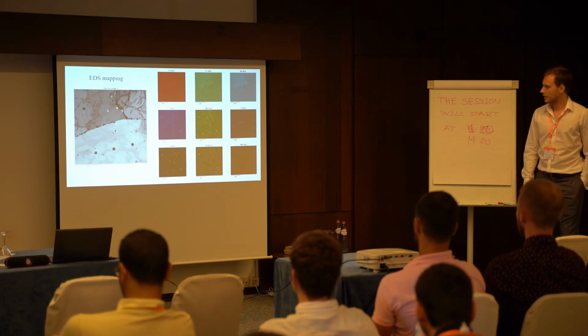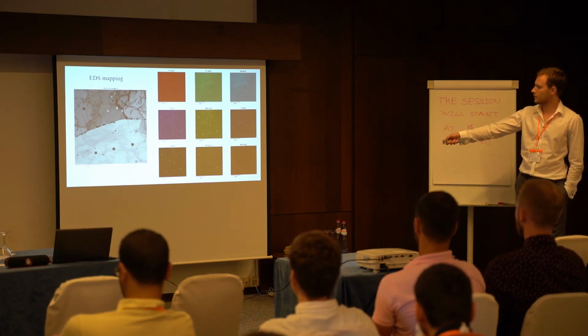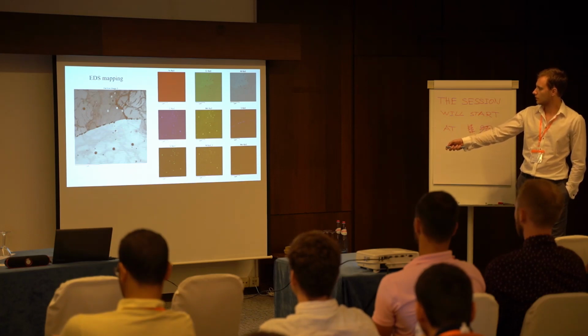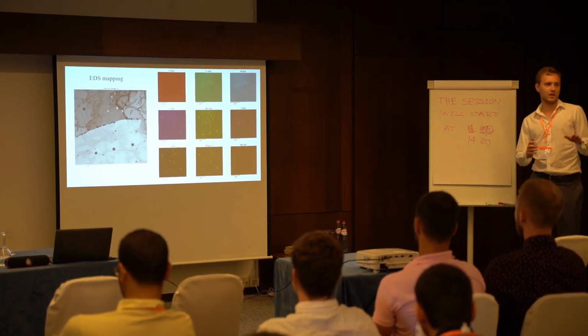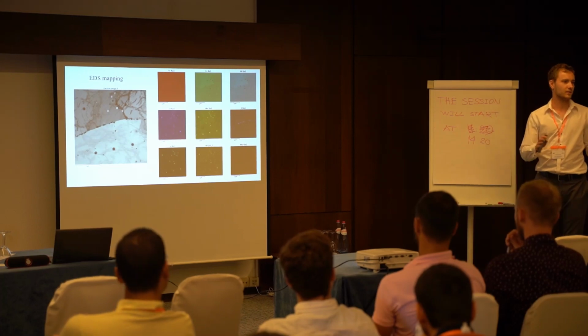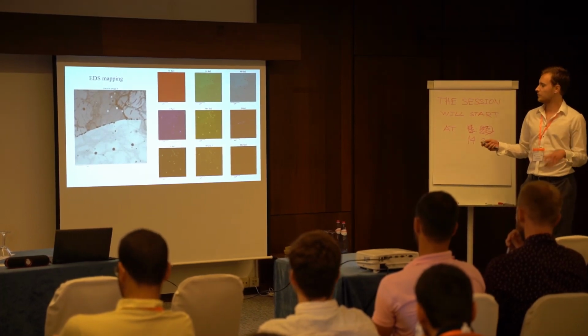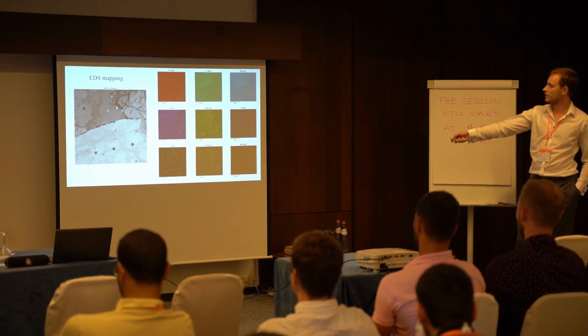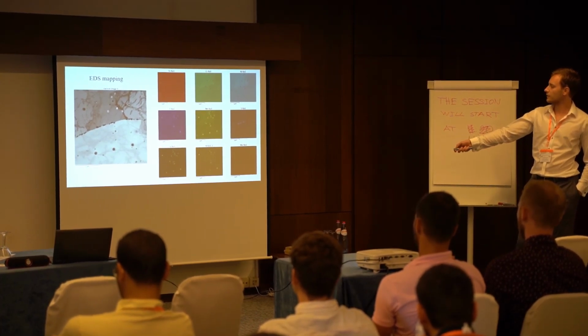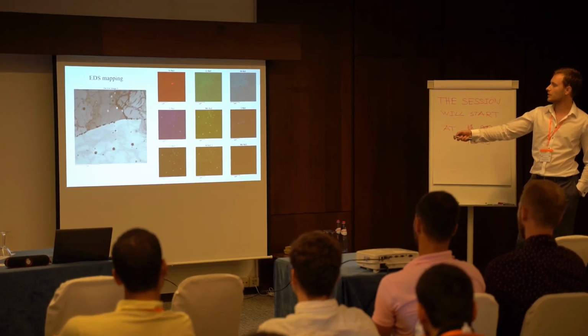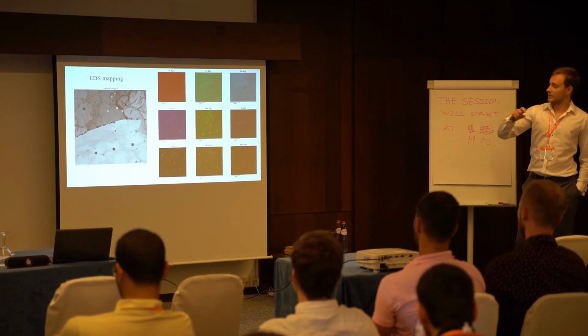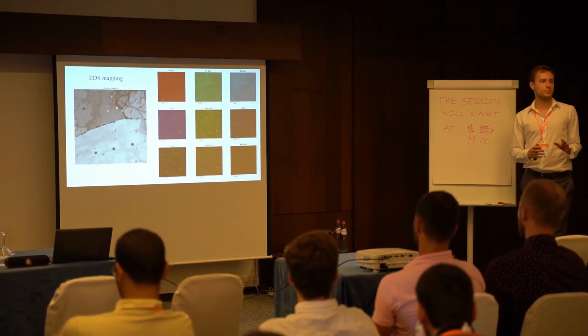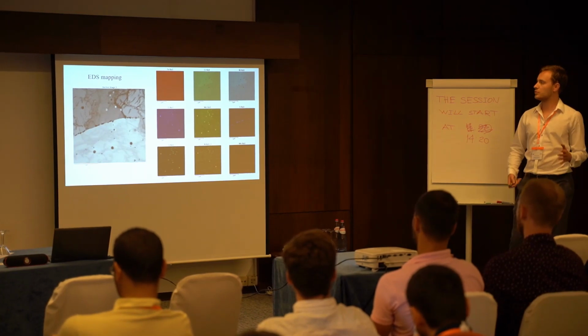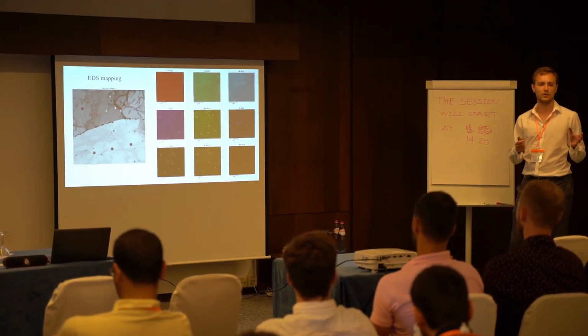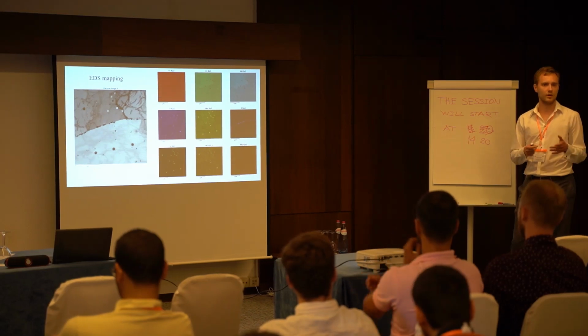So we did some EDS mapping, which, by the way, also proves what I said before, that these round particles are oxides, or possibly oxynitrides. With the nitrogen level I'm quite cautious because it's EDS, so one might be true, might be not. And these particles along the grain boundaries are first of all rich in molybdenum, depleted of iron and nickel, but interestingly they are not rich in chromium, which you would expect in steels. Usually chromium and molybdenum, as ferrite forming elements, segregate together, make carbides or whatever.